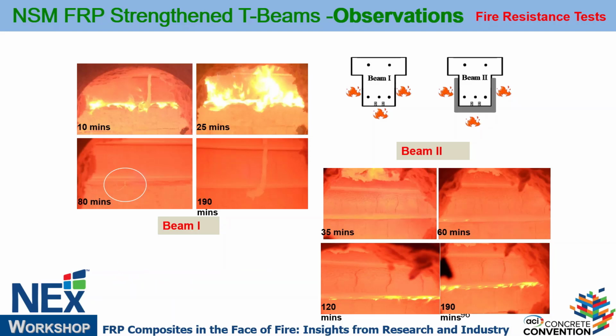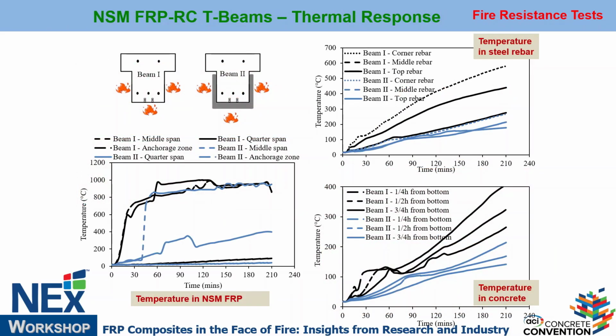It's not just the duration, but it's this as well. I don't have much time, but you can see here the temperature in the steel rebar. When you use it for strengthening applications, EB and NSM, the steel rebars are very important, because in case something happens, they have to continue to carry the load if FRP cannot carry the load. So keeping these steel temperatures cool, this is the steel temperature in the insulated beam. This is without insulation. So this is bad. That can lead to early failure.